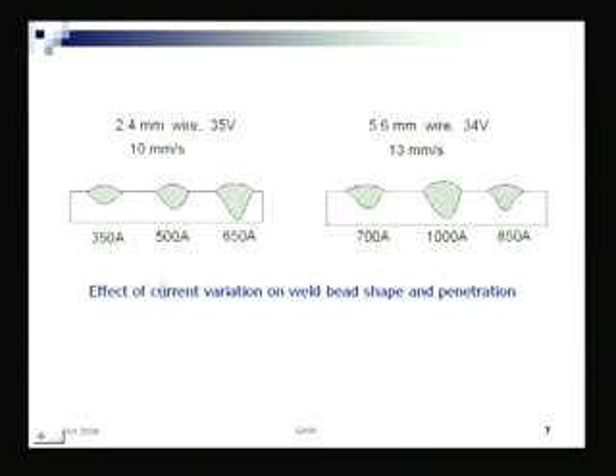So, schematically we can see that with this wire diameter, this speed and this voltage, arc voltage for a lesser current, and as we increase the current, it has the primary effect on depth of fusion. So, if a certain depth of fusion has to be achieved, you have to change the current, either increase it or decrease it.